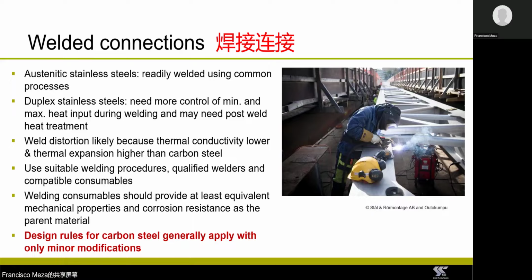Now, one important practical issue you should bear in mind, and this has already been mentioned by Nancy, which is in particular for when welding austenitic stainless steel, is to do with distortion. So stainless steel, and especially austenitic stainless steel grades, are more prone to welded distortion than carbon steel because they combine a lower thermal conductivity with a higher thermal expansion, which means that the heat remains more localized while the material expands and contracts more. So this means that when welding stainless steel, it is important to control the welding sequence and also provide adequate restraint to avoid distortions.